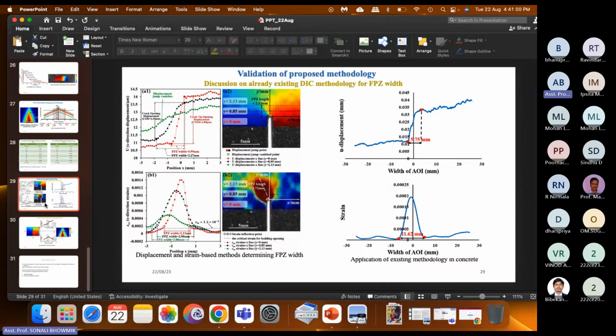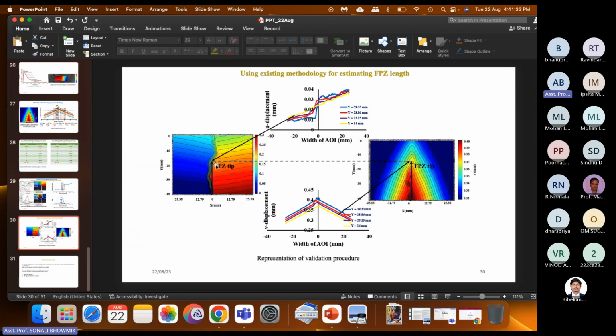So that's how it has been calculated, and finally we arrived at the conclusion that the size of the fracture process zone can be computed with the help of DIC analysis, and also of non-contact techniques like DIC analysis and other techniques like acoustic emission. This is the acoustic emission area where I also found out the fracture process zone size and the fracture patterns, which I have not included here, but this is an area where it can be fully verified with both non-contact techniques.